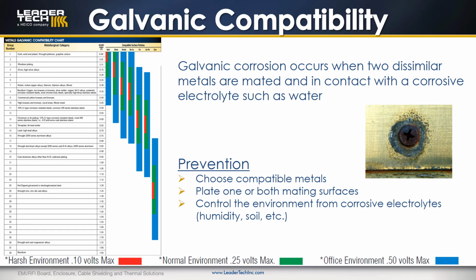For normal conditions, we recommend a max difference of 0.25 volts. This would be something like a warehouse that is not temperature or humidity controlled. And for controlled environments, we recommend a difference of 0.5 volts max. The best prevention for galvanic corrosion protection between the enclosure shielding gasket and mating surface is to choose compatible metals, plating on one or both of the mating surfaces, and controlling the environment from things like humidity or soil.